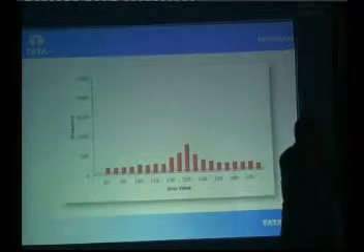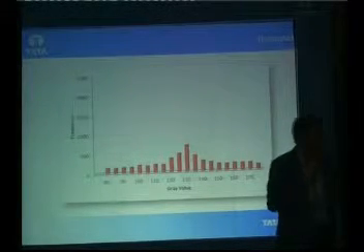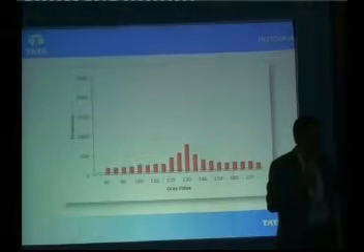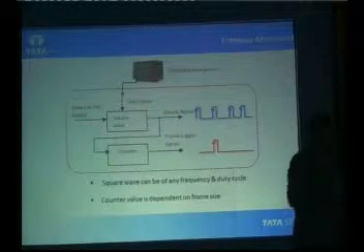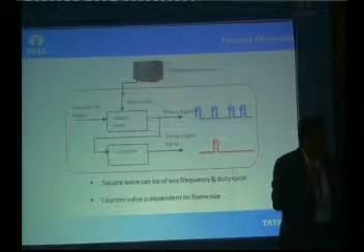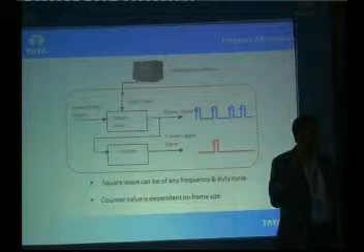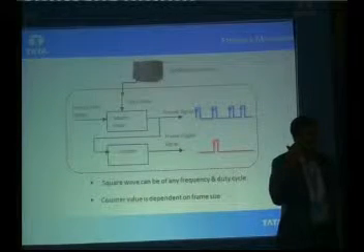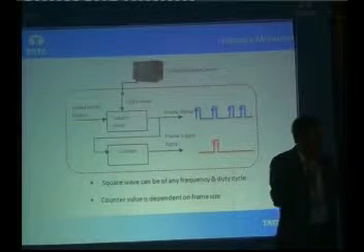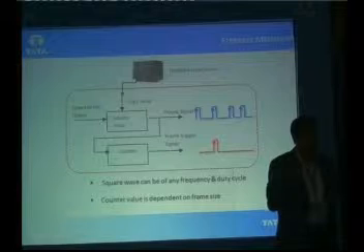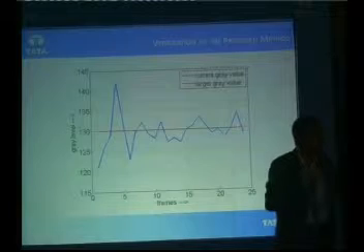If we plot the histogram, we can see that without any exposure control, the histogram is widely spread across all the gray value bins. So what we did: we take the reference of the speed of the object and the gray value, which is the feedback from the previous frame. Is it low? Then we increase the exposure by a certain amount if the target level is higher, and decrease it if the target level is lower. By that virtue, we generated a feedback mechanism which gives a constant gray value for each and every frame. So this is the result.